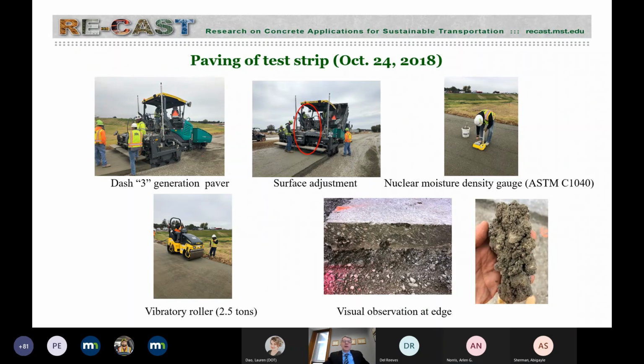So moving to the job site, we did 1 day of a lot of testing of mixing, placement, and consolidation, to adjust really the placement and consolidation energy. We measured the density using a nuclear moisture density gauge and different number of passes of this small vibratory roller, which is 2.5 tons. And then you see the paver.